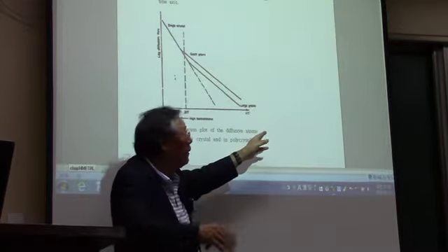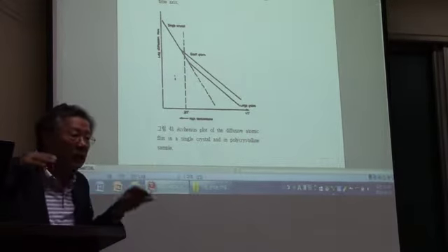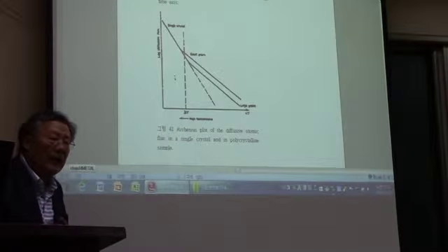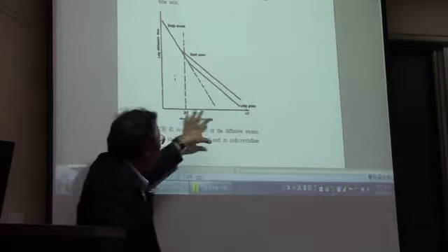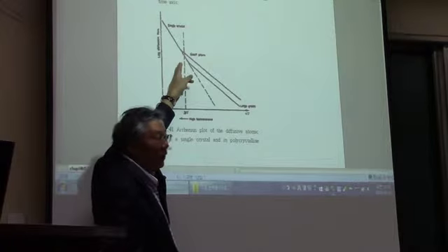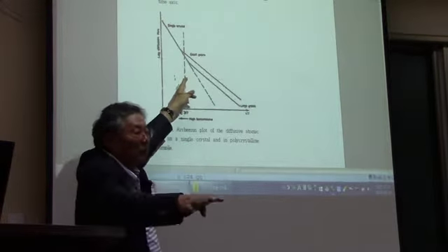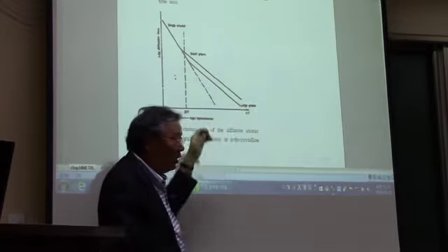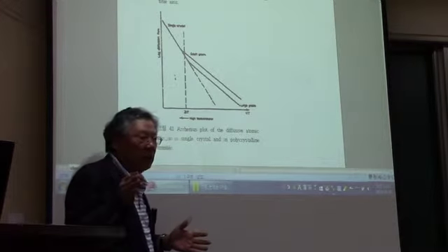But if you move to high temperature, then intragrain diffusion can happen, because you have high enough thermal energies. Okay, so in this experiment, at high temperatures, the diffusion coefficient we have represents the diffusion coefficient in the material. But as you move to lower temperature, only diffusion along the grain boundaries will happen, so